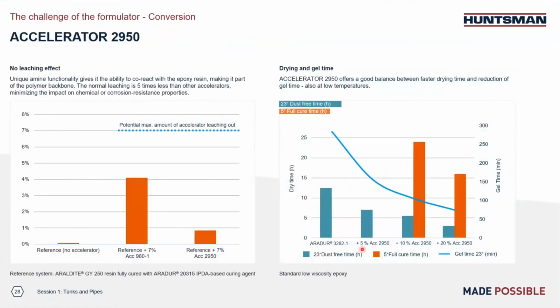Like I mentioned earlier, the accelerator 2950 has amine functionality, right? So it will cross-link to the polymer matrix backbone, so it won't leach out and compromise the performance. So here's a test we did. This reference test is based on Araldite GY250 with IPDA-based curing agent 20315. This is the reference, since we did not add any accelerators. After the panel was made, we cut it into small pieces, and then we soaked it in the solvent to see how much we can extract out.